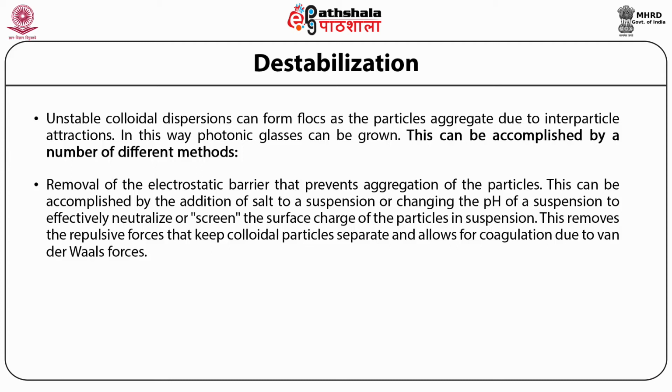This can be accomplished by the addition of salt to a suspension or changing the pH of a suspension to effectively neutralize or screen the surface charge of the particles in suspension. This removes the repulsive forces that keep colloidal particles separate and allows for coagulation due to van der Waals forces.